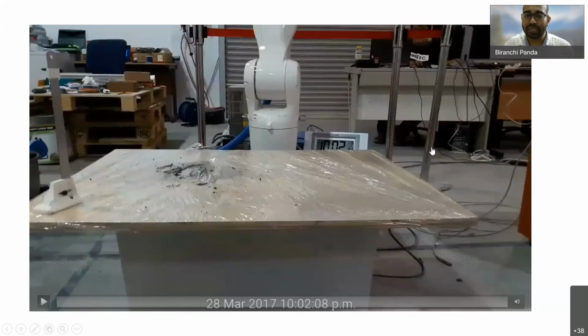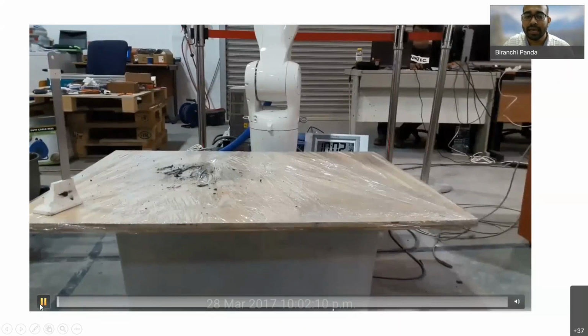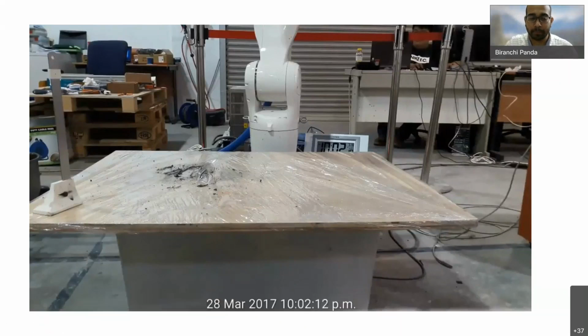So as you know, in concrete we always add water to mix the material, but for this competition we developed a new material which required very less water, as the competition targets to use the minimum amount of water. So we developed another polymer known as geopolymer for this application. As they mentioned in the competition, we have to use an automated system. So we had a small robot in the laboratory. We just converted it into a printing process, and you can see that with our newly developed geopolymer material, we were able to print some structures for them.